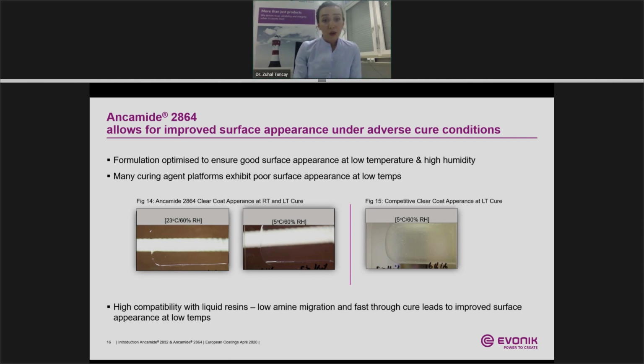Like you see in figure 14, 2864 delivers very good surface appearance at ambient and at low temperature and at high humidity due to its fast cure, excellent compatibility with liquid epoxy resin, and its low amine migration. Compared to this, many curing agents deliver poor surface appearance at low temperature, which was the case in figure 15.